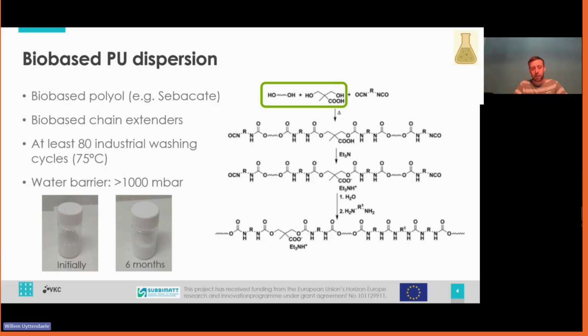And even after washing 80 times, we still have a water barrier of more than 1000 millibar, which is the pressure of about 10 meters of water. The dispersions also stay stable, so even after 6 months, we have a perfectly stable bio-based polyurethane dispersion. So this is really a good candidate to replace fossil-based polyurethanes. It has the properties it needs. But of course, as Lutz mentioned, there is a slight premium when it comes to these bio-based polyurethanes.